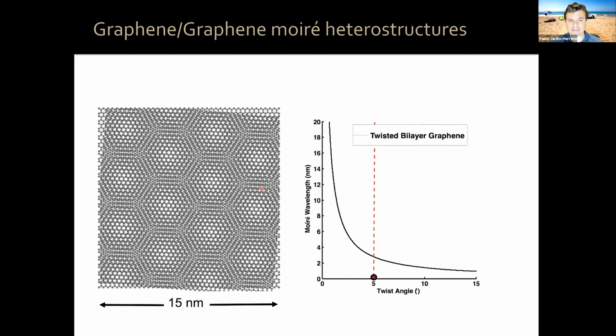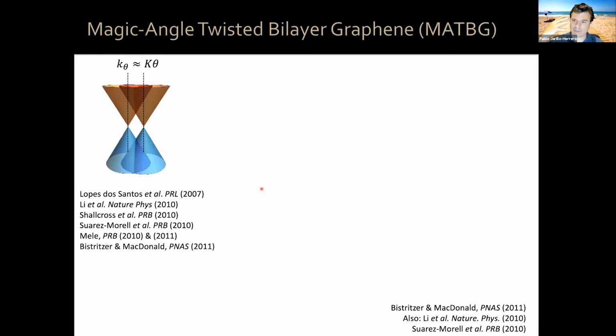This is what happens in real space. What happens in momentum space, and therefore what happens to the electronic structure? So let's start with a small angle, where already the distance between the Dirac cones in momentum space, these are the Dirac cones from layer 1 and from layer 2, is proportional to the twist angle. Now, this would be a situation that would occur if these two graphene sheets did not know about each other. However, the electrons in these two graphene sheets are only spaced by 3 angstroms, so they're very much aware that the other graphene sheet exists, and in particular, they can tunnel between the sheets.